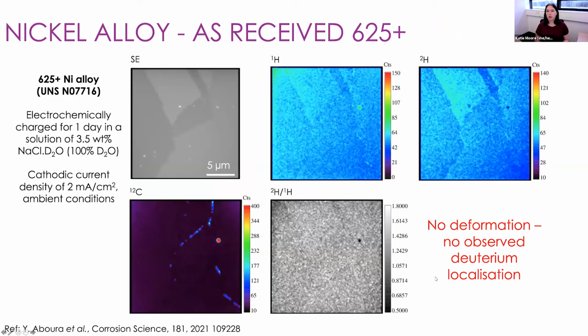So I now want to show some work on the nickel alloys that Yasser was looking at. We were first looking at this alloy 625 plus, which was of interest for BP, who funded this project. The first thing we did was to look at the as received 625 plus. If we look at the deuterium over hydrogen ratio image, we do not see any localized regions of deuterium. So we have no deformation and we see no localized deuterium.